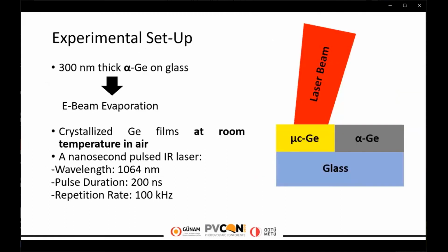In this experiment, an amorphous germanium film with a thickness of 300 nanometers was deposited on a glass substrate using the e-beam evaporation technique. The amorphous germanium film was crystallized using a nanosecond pulse infrared laser at room temperature in air. A nanosecond pulse infrared laser with a pulse duration of 200 nanoseconds and a repetition rate of 100 kHz at a wavelength of 1064 nanometers was employed.